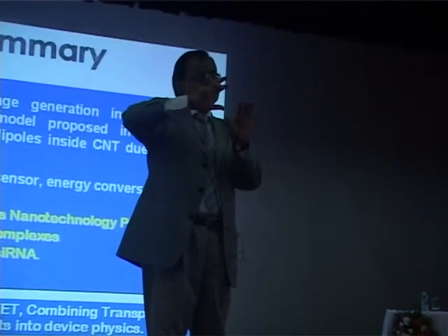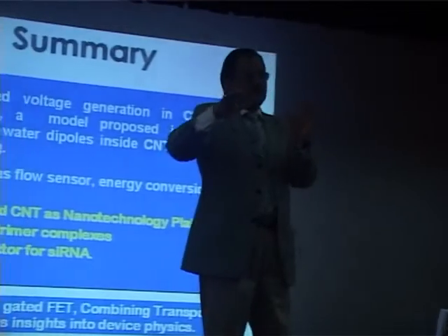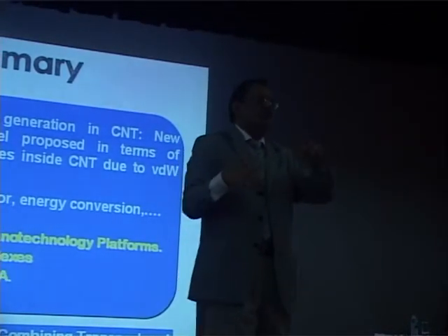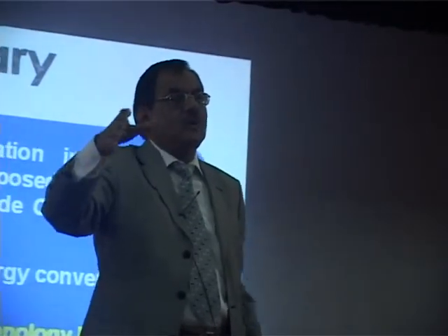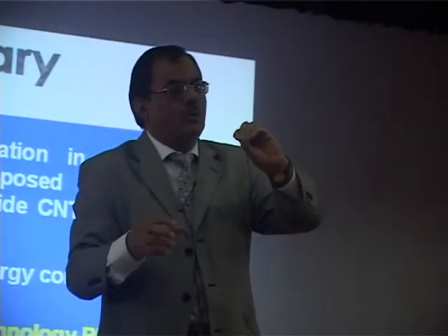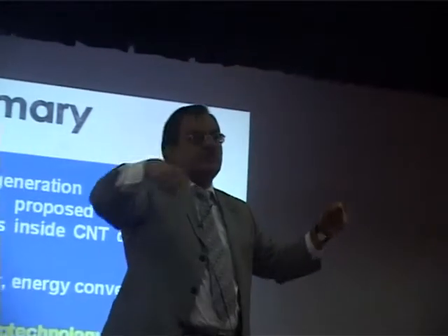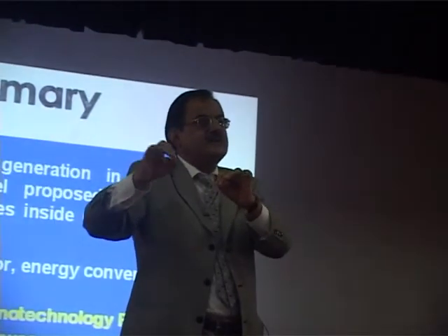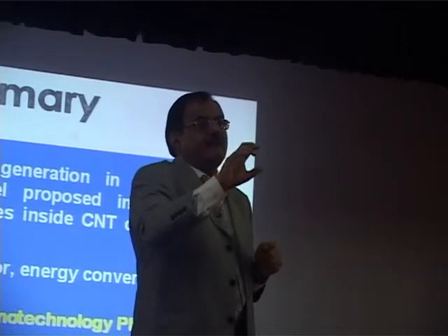Okay, I think as I said, because these are fast devices, because you have the high mobility, only in the fast devices it will have a niche, but the semiconductor industry is extraordinarily well developed. So there is no competition to silicon devices. But now the emphasis is on fast devices, maybe resistive switching devices and so on, where there is a niche. But I should not leave you with the thought that it is happening tomorrow. Point is, the on-off ratio of these devices is still very low because they don't have a band gap, right? Because there is no valence band, conduction band separation. So this has to be tackled to make a slightly larger gap without losing the mobility advantage. So in that context, graphene has a good role.